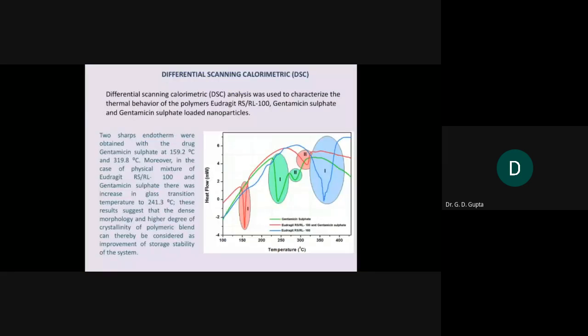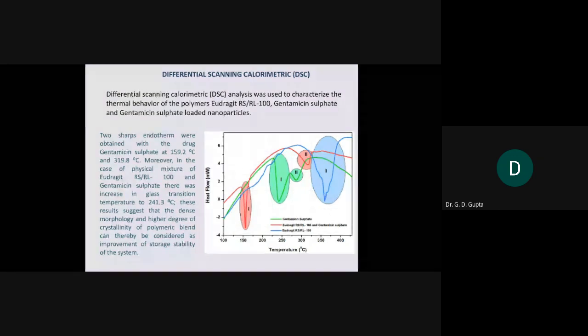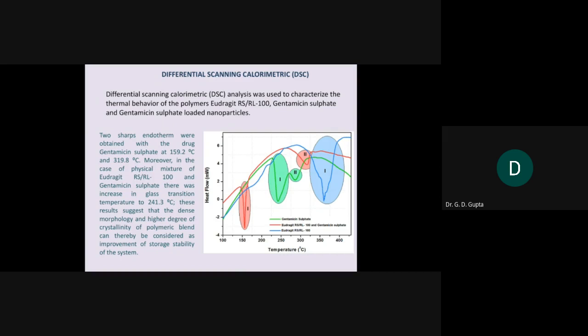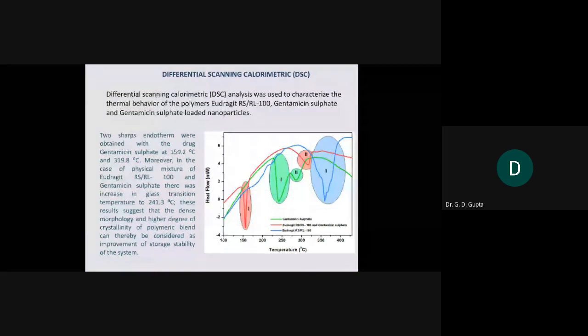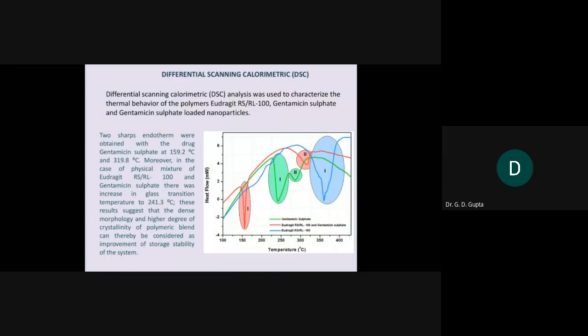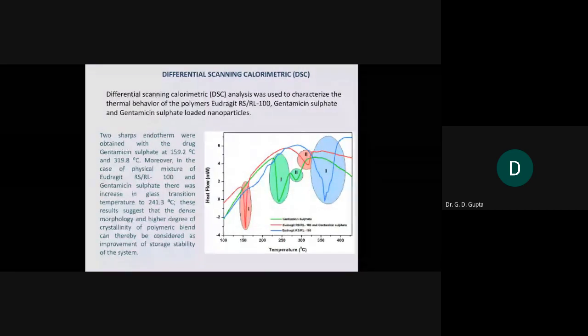Second one is differential scanning calorimetry, and this analysis is used to characterize the thermal behavior of the polymer Eudragit RL100 and the drug gentamicin sulfate, as well as the polymeric nanoparticle which contains the drug. Now you can see two sharp endotherms were obtained with the drug gentamicin sulfate, near about 160 degrees centigrade, and another about 320 degrees centigrade. Moreover, in the case of the physical mixture of Eudragit RS RL100 and gentamicin sulfate, there was an increase in the glass transition temperature near about 240 degrees centigrade. These results suggest that the dense morphology and the higher degree of crystallinity of the polymer blend can thereby be considered as an improvement of the storage stability of the system.